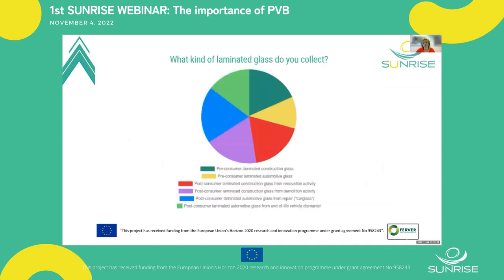This slide is interesting because the results show a variety of types of laminated glass that are collected and processed. And for every category, we see similarities in the responses. The first two categories, the dark green and yellow colors, correspond to pre-consumer laminated glass. The first one, the dark green, is for the construction sector, and the second one is from the automotive sector. In general, pre-consumer streams are of better quality as they come from production cuts that are not contaminated by other materials.